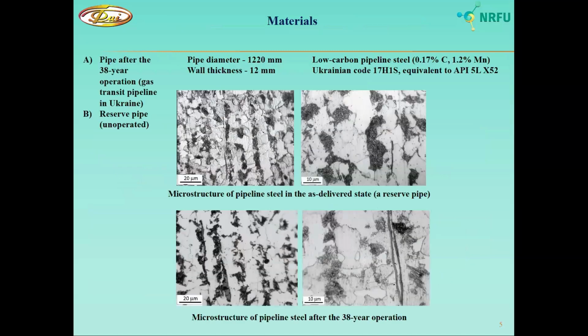So the material under study was a low carbon pipeline steel with X52 strength grade from two pipes after 38 years of operation on a gas transit pipeline in Ukraine, and for comparison, a reserve unoperated pipe of the same grade steel. Both pipes have the same diameter and wall thickness. So specimens cut out from these pipes longitudinally and transversely were subjected to characterization, hydrogen charging, testing, and analysis.